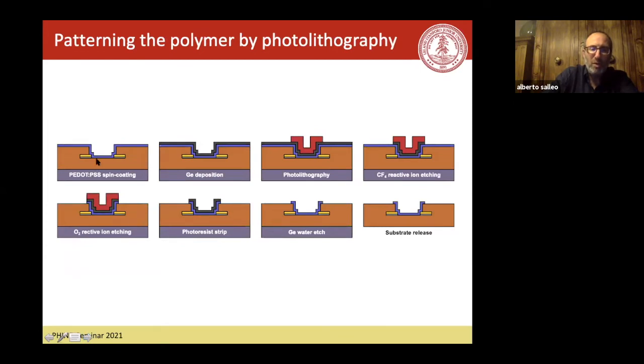But now is the challenging part, which is to deposit the sensing polymer between these two electrodes. And so the way to do it is you deposit the polymer, and this is a process developed by Nick Melosh, and then you put a protective layer on top of it. But the protective layer has to be quite delicate as well. You have to be able to remove it in the end without damaging the polymer. It turns out germanium is a great protective layer, because germanium oxide is actually etched in water. So that's a very gentle etch, but germanium itself is quite resilient.